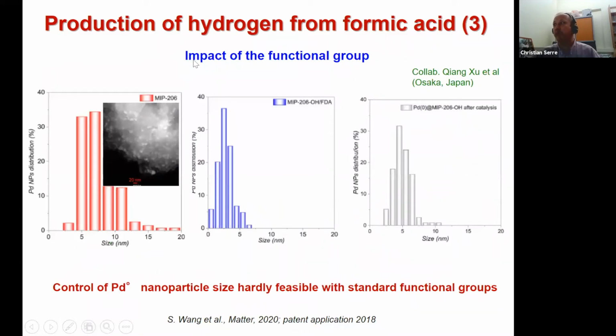As we could vary the nature of the functional group on this solid, of course, it was natural to look at the consequence in terms of catalytic activity. But first of all, we were interested to see where the palladium nanoparticles are. If you take the bare MOF, clearly, if you look at the particle size distribution from TEM, we can say that they are probably at the outer surface of the particle or localized in defects inside the crystal, because the particle size is much larger than the pore size of the MOF.